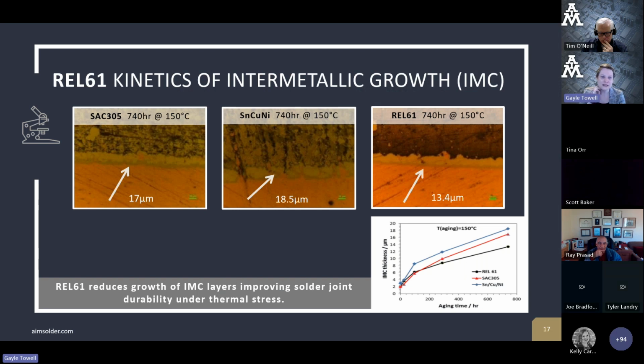Here we're looking at kinetics of intermetallic growth. It tends to reduce the IMC layers a little bit, which can improve solder joint durability under thermal stress. So here it is just in comparison to SAC305 and a tin copper nickel alloy.